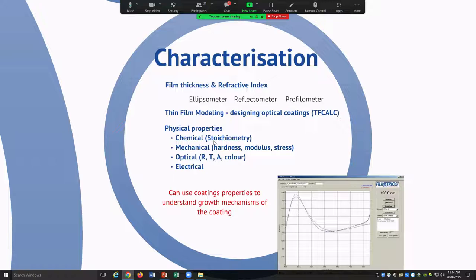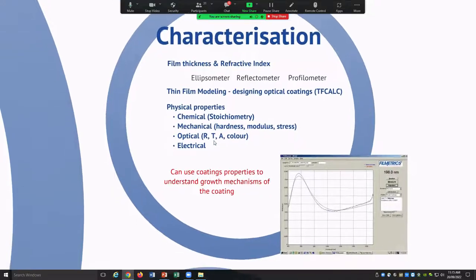Chemical, the mechanical properties. Stress is very important in thin films. If you're putting coatings onto a plastic, if the coating's too stressed, it's going to crack and craze. So minimising or controlling or just even measuring stress is important. If you're doing electrical components, electrical layers, then obviously the electrical properties of your coating is important. And understanding how your deposition conditions affect all of these properties is part of developing thin film coatings.